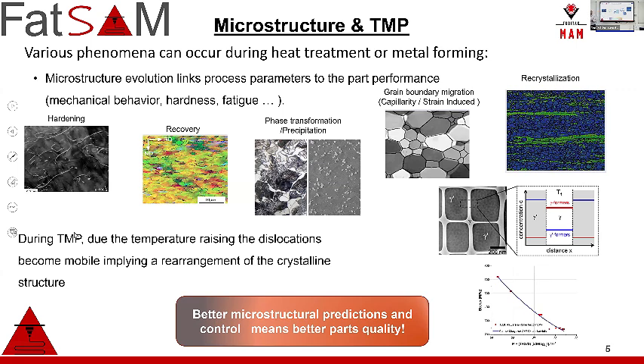In high temperature applications, we are looking not only for ordered grain structure or fine grains. Actually, we are looking for coarser grains, which also prevent dislocation motion during high temperature deformation or loading. During TMP, due to temperature rising, the dislocations become mobile, and in most of the creep and fatigue tests at high temperature, the main active mechanisms are dislocation motion, grain boundary sliding, or grain boundary diffusion. And the purpose, at the end of the day, is that we would like to improve high temperature life or rupture time of the materials.